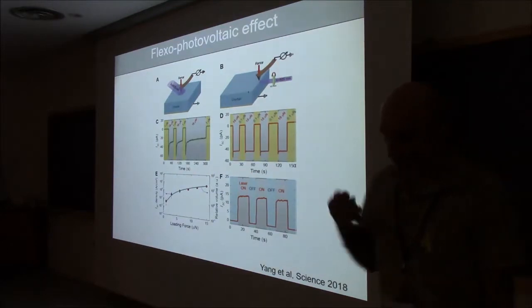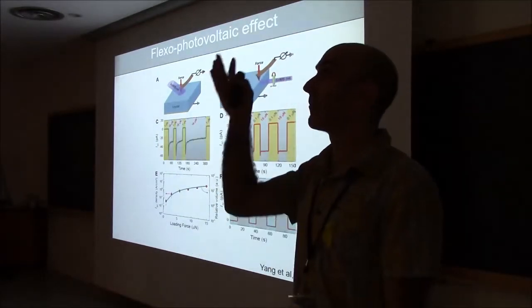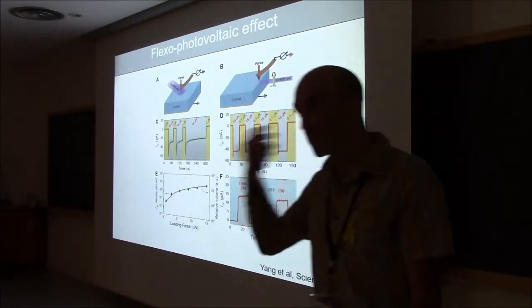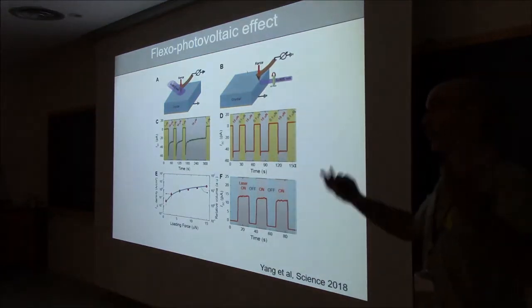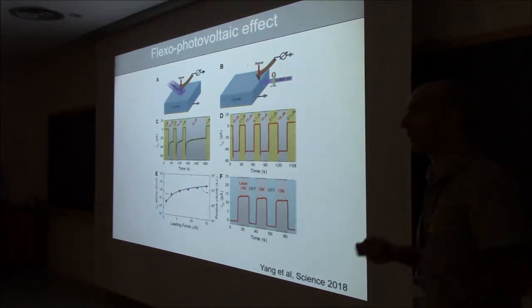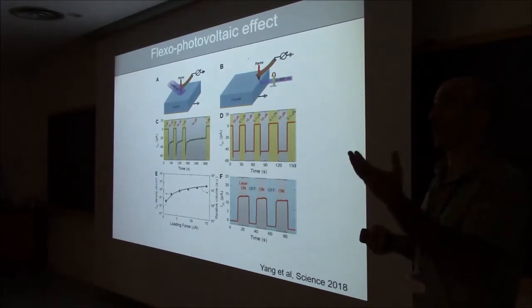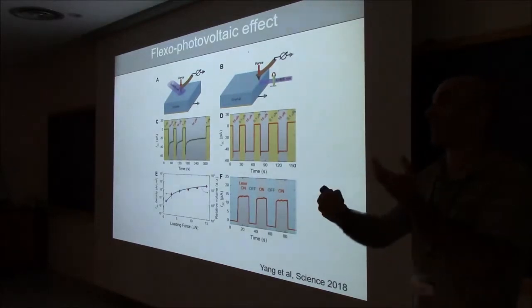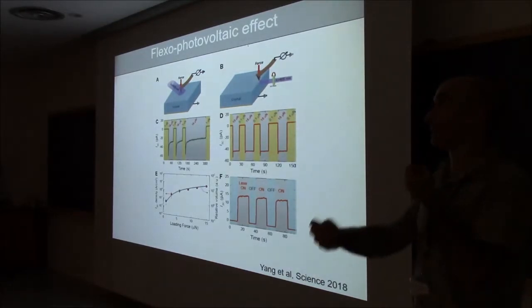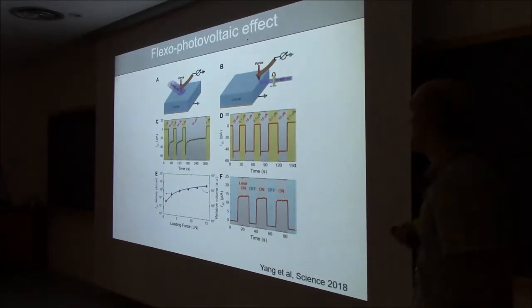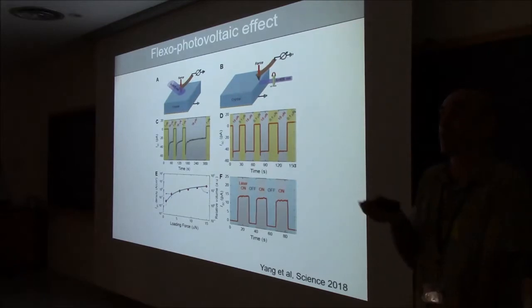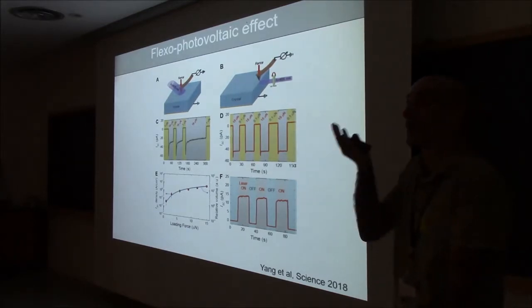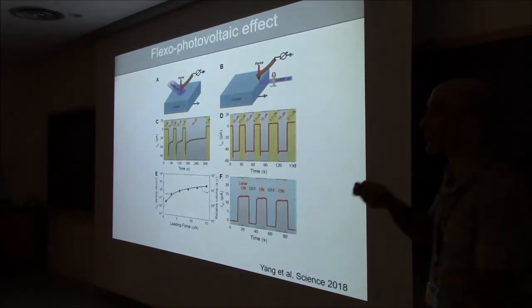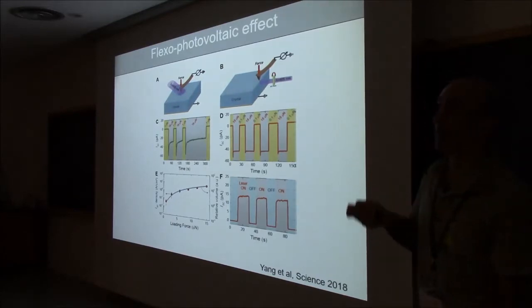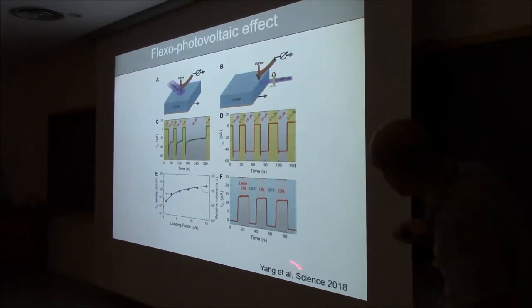If you remember when I was talking about the bulk photovoltaic effect, you have a material that is polar, non-centrosymmetric, and you shine light on it, the asymmetry of the lattice separates the charge carriers and gives you a current or a photovoltage. And that's called the bulk photovoltaic effect. That only exists in materials that are non-centrosymmetric. But of course you can also break centrosymmetry, or break symmetry, by a strain gradient. And that's what Marin Alexe and Ming-Min Yang have done.